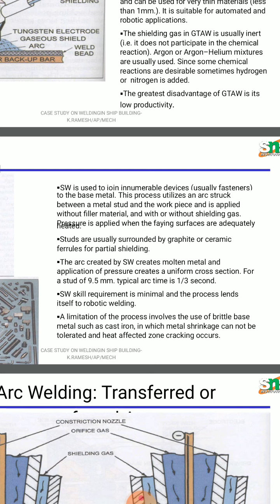For a stud of 9.5 millimeter, typically arc time is 1/3 second. The skill requirement is minimal and the process lends itself to robotic welding. A limitation of the process involves the use of brittle base metal such as cast iron, in which metal shrinkage cannot be tolerated and heat affected zone cracking occurs.